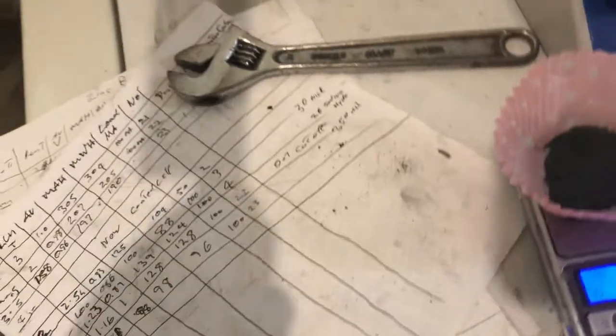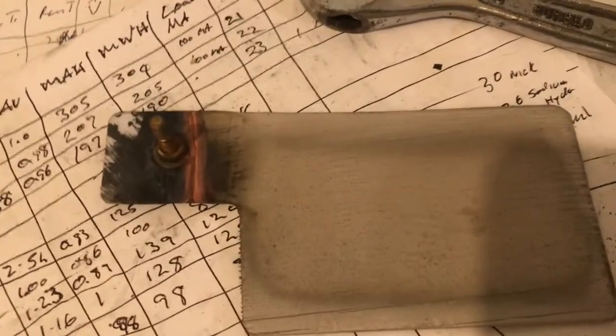So that's around about an hour and 45 minutes, and we're looking good. So we haven't broken. It was only breaking because it was maybe chrome or something and not nickel, and it may also be the ammonia in that ammonia nickel sulfate. So at a later date I'll do another small little batch and test to see if it will actually plate over. But for now I've got a working electrode.